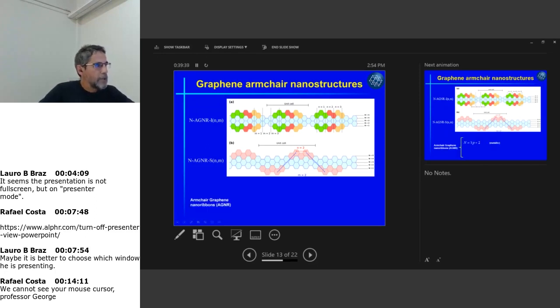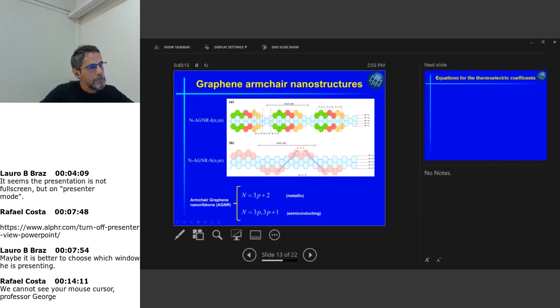So you should know that armchair graphene nanoribbons, which are the AGNR here in this terminology, can be metallic if they have capital N equal 3p plus 2. So for example, this N equal 5 backbone of my heterostructure here is an armchair graphene nanoribbon that is metallic, because for p equal 1, this gives me 5. So I know that N equal 5 is metallic, and the other two possibilities are 3p and 3p plus 1. So for example, an armchair graphene nanoribbon with N equal 3 or N equal 4, both of them are semiconducting. And the gap decreases as N increases, and goes to 0 every time that I pass through 3p plus 2.